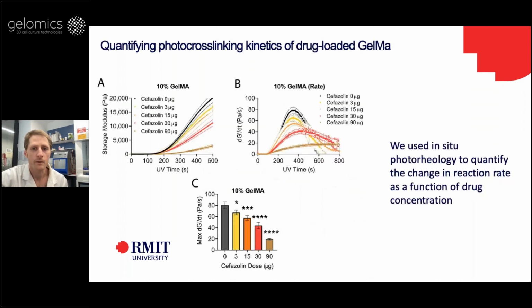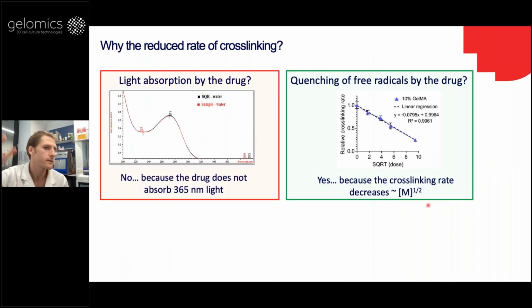So we did some in situ photorheology and found that the rate of the reaction was totally different across samples with different amounts of the drug. And as you add more cefazolin, the reaction rate drops. It was quite a dramatic drop. The question is why. So one idea might be that the drug is absorbing light and therefore reducing the light intensity.